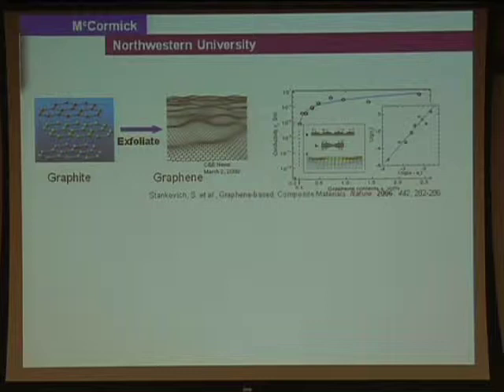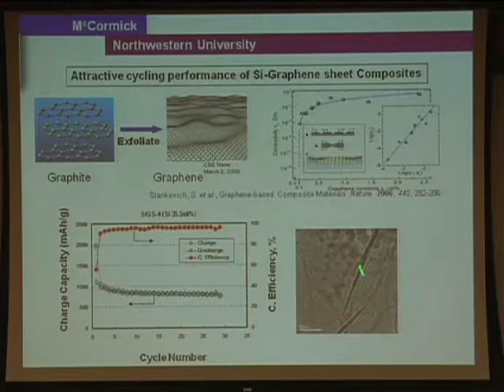So one can think of using this kind of material as part of the package for the silicon to make the anode. Indeed, this can be done. These are the graphene layers here, and these are the little silicon nanoparticle dots that I showed you in the last slide. And this is then the stability in the charge-discharge cycle in terms of the maintenance of the charge capacity.